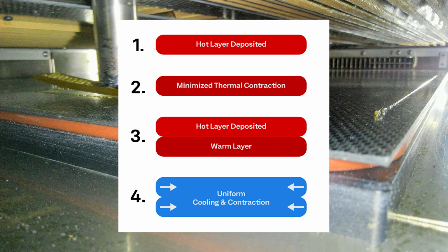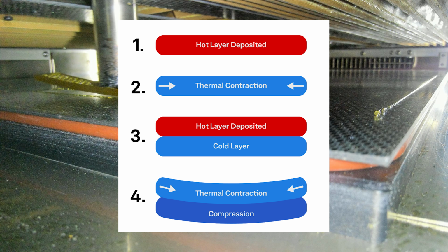As the polymer cools, it shrinks. In a properly heated chamber, that cooling is delayed, allowing the part to contract uniformly after the build. In a colder chamber, shrinkage begins almost immediately after deposition, creating residual stresses that eventually warp the part or cause layers to separate.